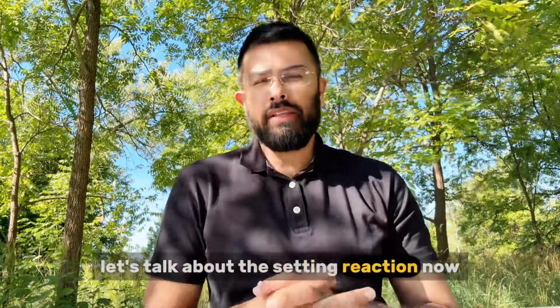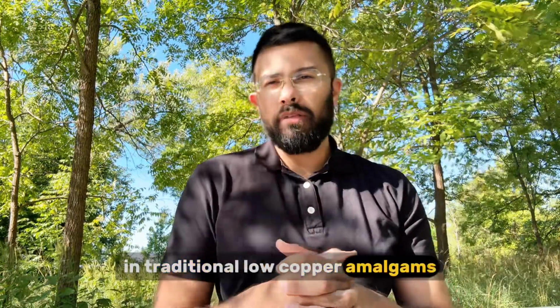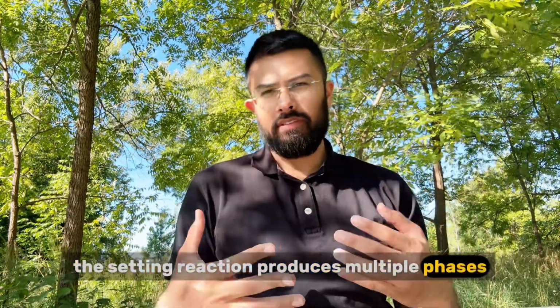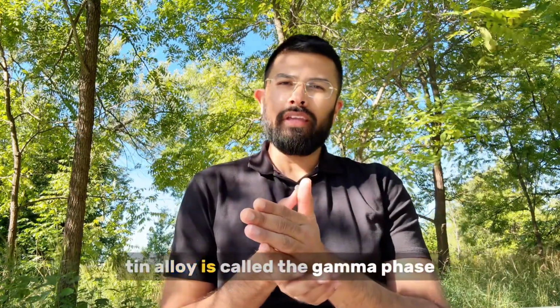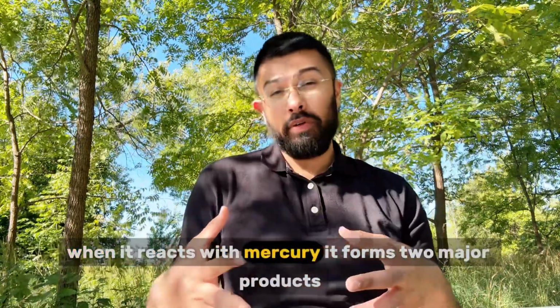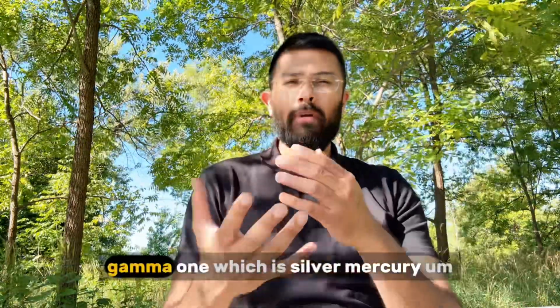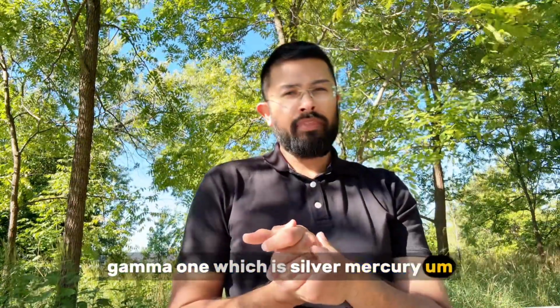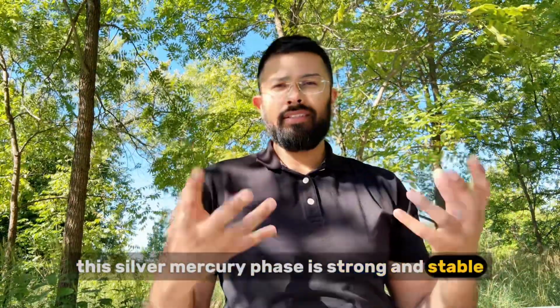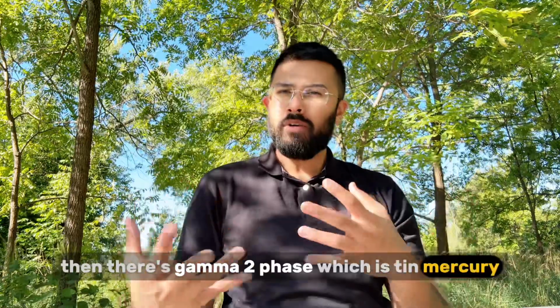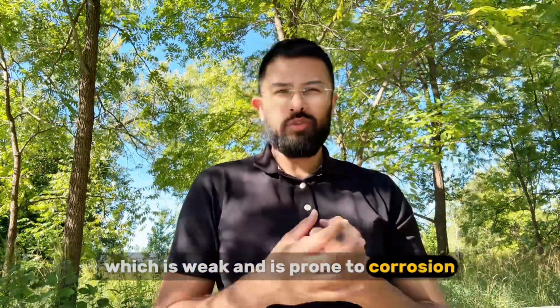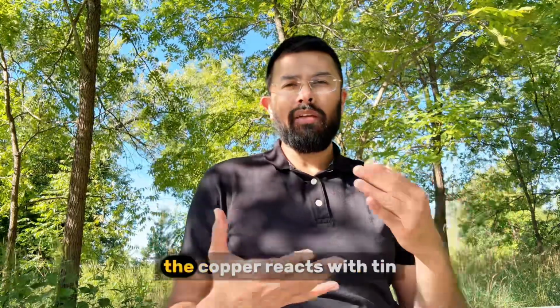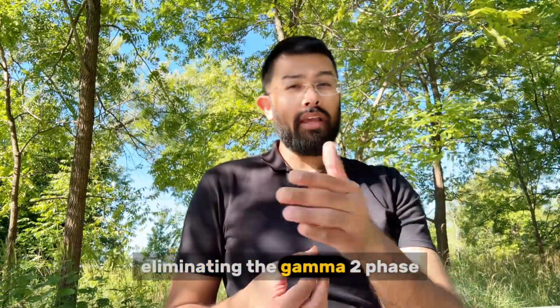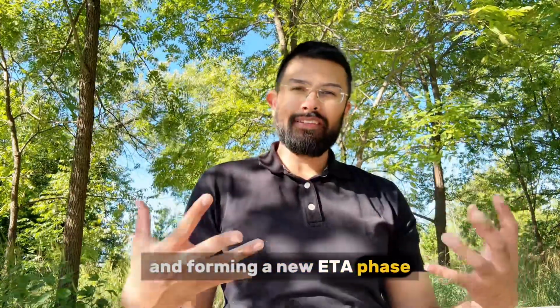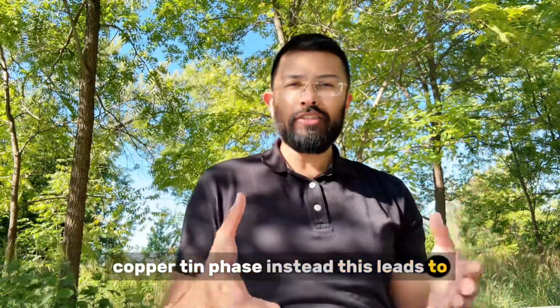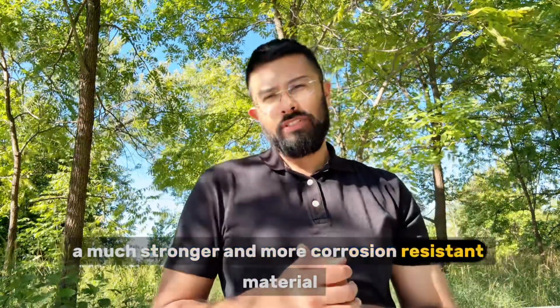Let's talk about the setting reaction now. In traditional low copper amalgams, the setting reaction produces multiple phases. The unreacted silver tin alloy is called the gamma phase. When it reacts with mercury, it forms two major products. Gamma 1, which is silver mercury. This silver mercury phase is strong and stable. Then there's gamma 2 phase, which is tin mercury, which is weak and is prone to corrosion. In modern high copper amalgams, the copper reacts with tin, eliminating the gamma 2 phase and forming a new eta phase, copper tin phase instead. This leads to a much stronger and more corrosion resistant material.